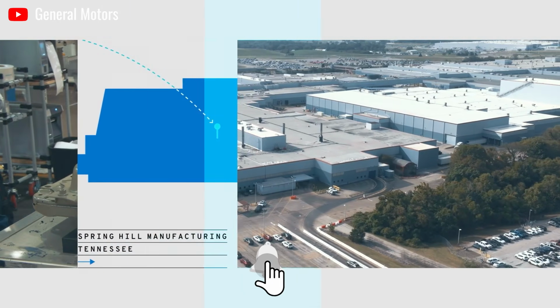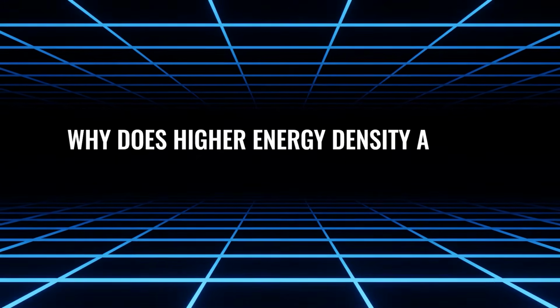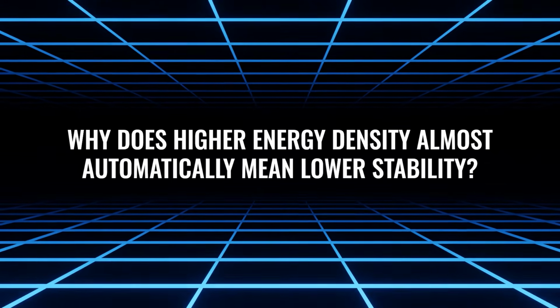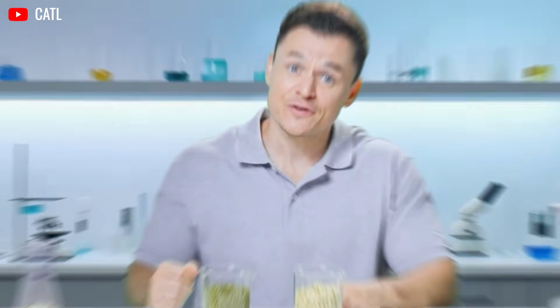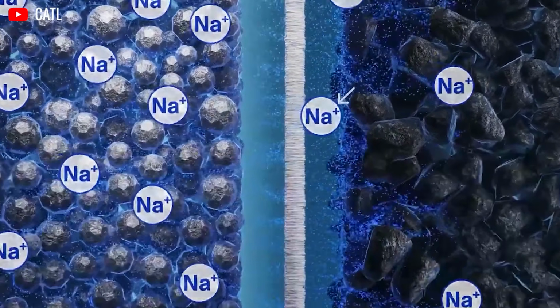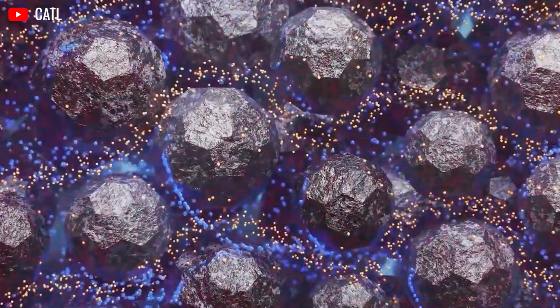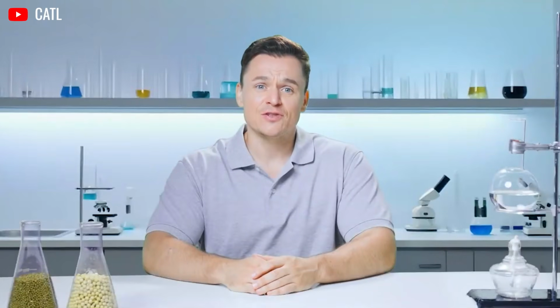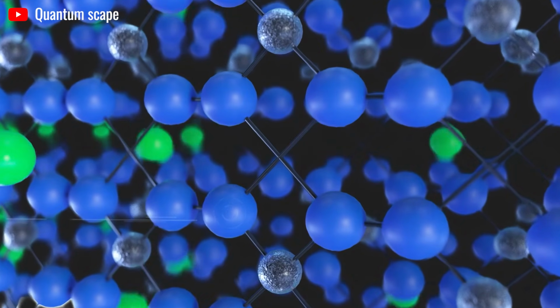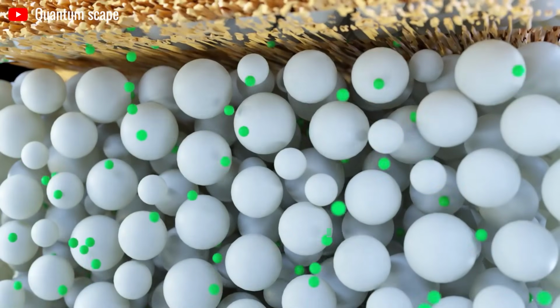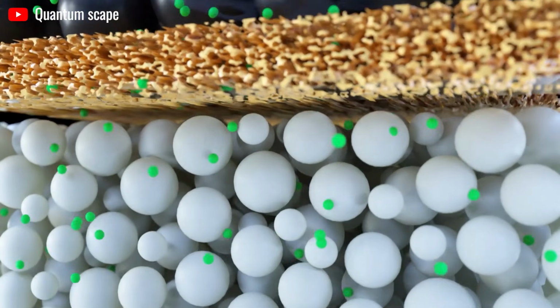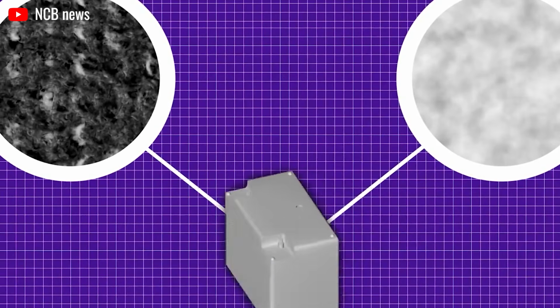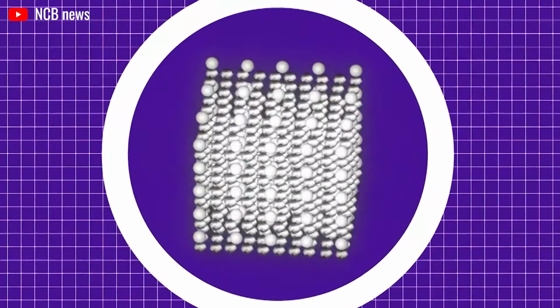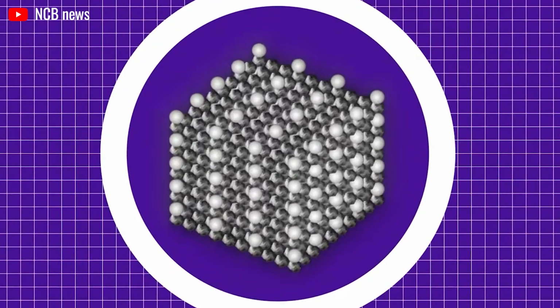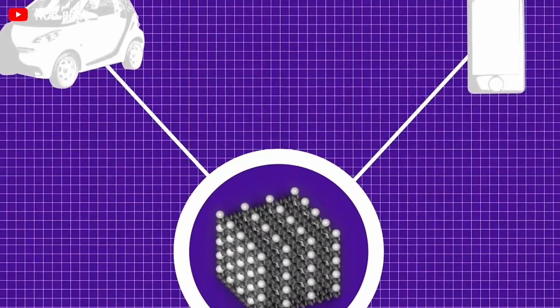Why does higher energy density almost automatically mean lower stability? At the atomic level, storing more energy means forcing electrodes to operate closer to their chemical and electrochemical limits. Bonds that are comfortable and stable at lower energy densities become strained when we demand more electrons per unit mass. In practical terms, this is why lithium-metal anodes and high-nickel cathodes look so attractive on paper yet behave so badly